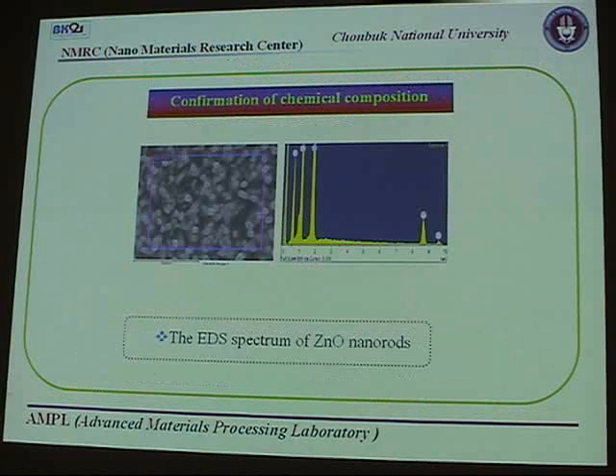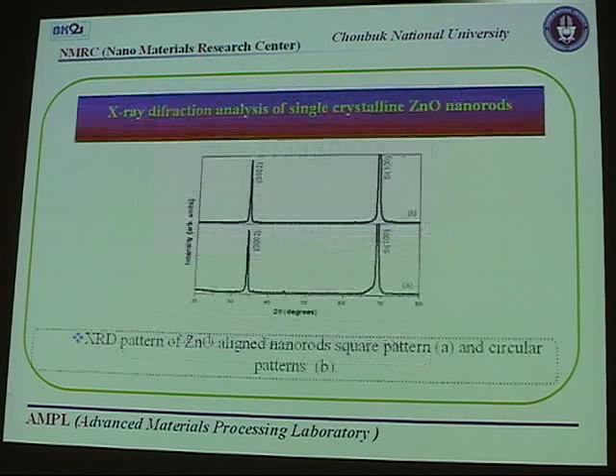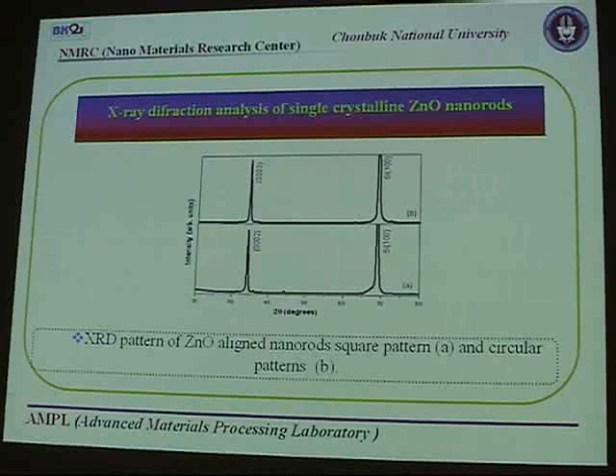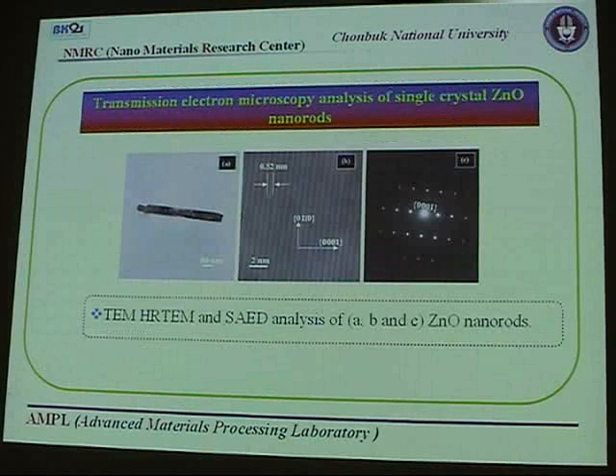We did chemical confirmation of the zinc oxide nanorods using EDX, which shows that these nanorods are completely composed of zinc and oxygen. The silicon peak appears due to the substrate. The XRD diffraction pattern confirms that these zinc oxide nanorods are single crystalline because it shows a high intensity 002 peak, which confirms that they are well oriented on the substrate and grown along the c-axis direction. Further structural confirmation is done by transmission electron microscopy, which shows that these zinc oxide nanorods are single crystalline in nature.